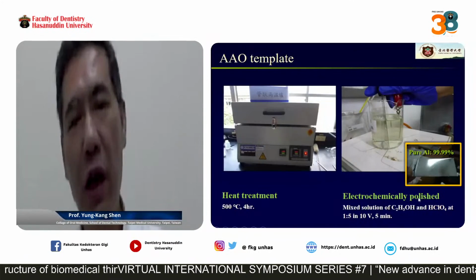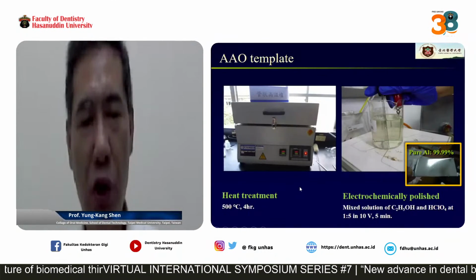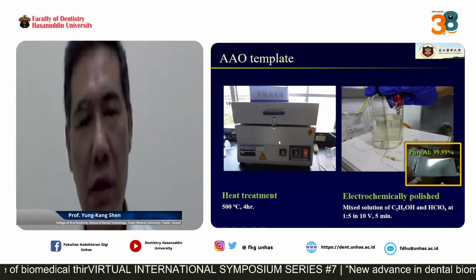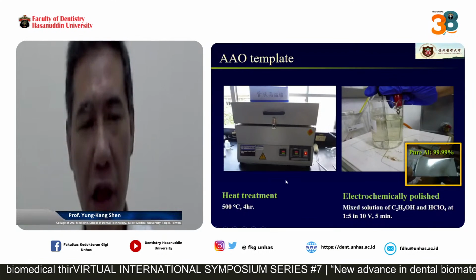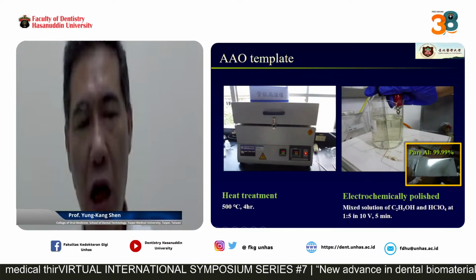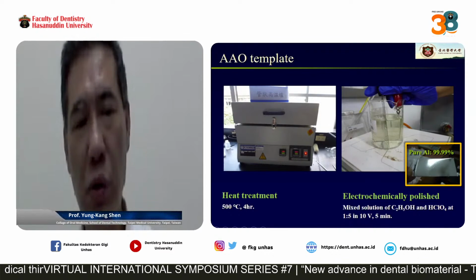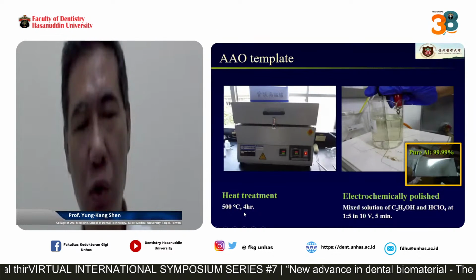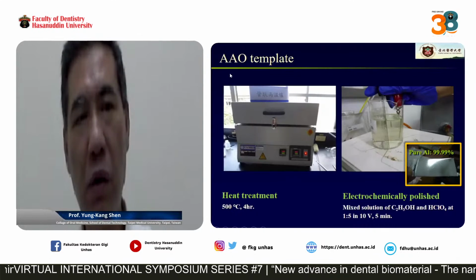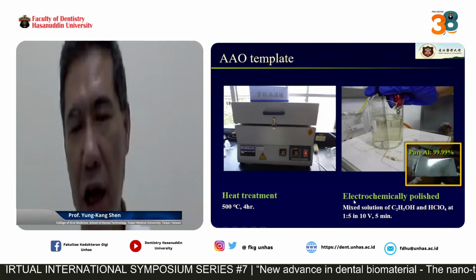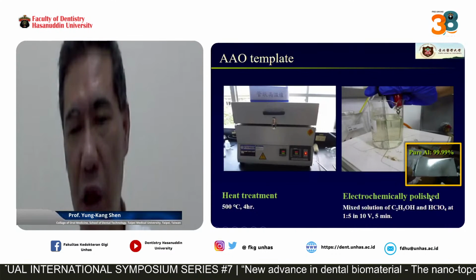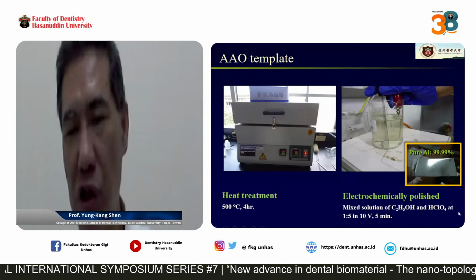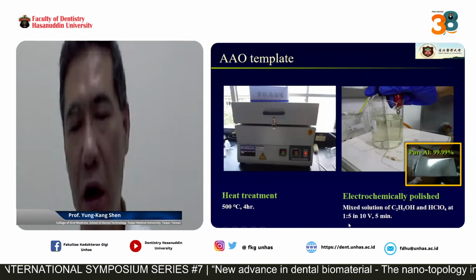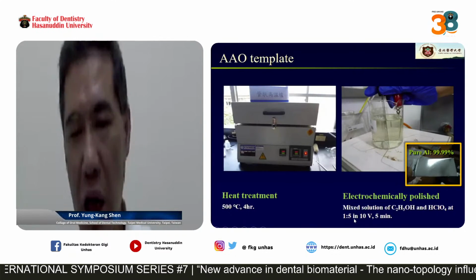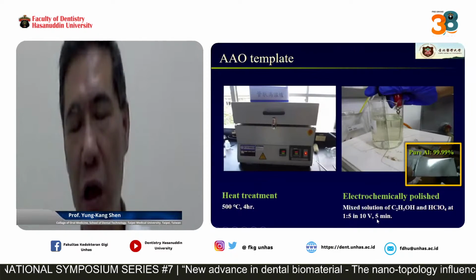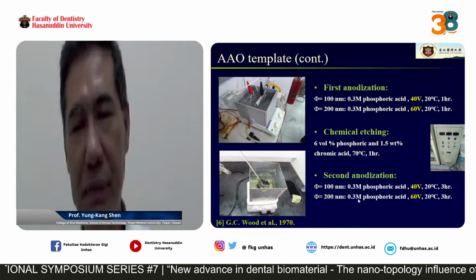So how do we make the AAO template? First, we must use so many pieces of equipment here. This is the heat treatment. Here, we use 500 degrees C and do the heat treatment for 4 hours to manufacture the Al tablet. And for the electrochemical polishing, we use C2H5OH and HClO4 at a 1:5 ratio at 10 volts. The processing time is 5 minutes.